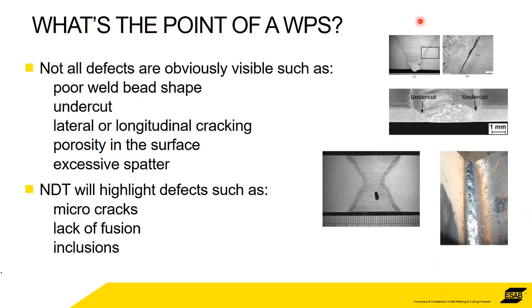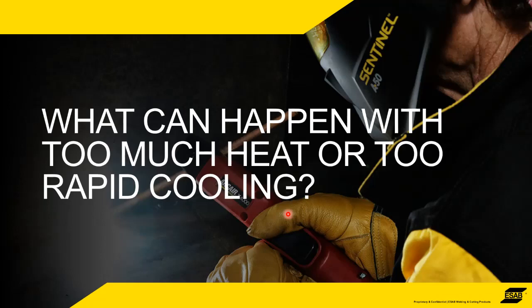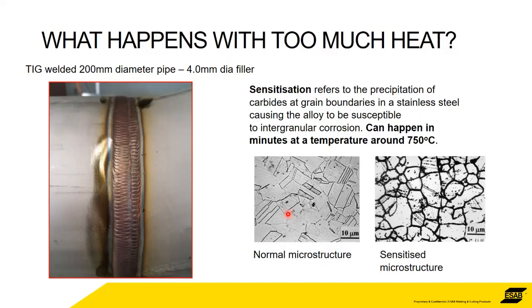Even the basic NDT methods will highlight any micro cracks or lack of fusion in the sidewall, or indeed inclusions or porosity within the weld itself. So you can do that with NDT. Yeah, that's fine. However, some of these problems occur that are not visible and are not possible to detect with NDT. So what happens if you ignore the parameters for interpass and heat input, or you cool things down too quickly?